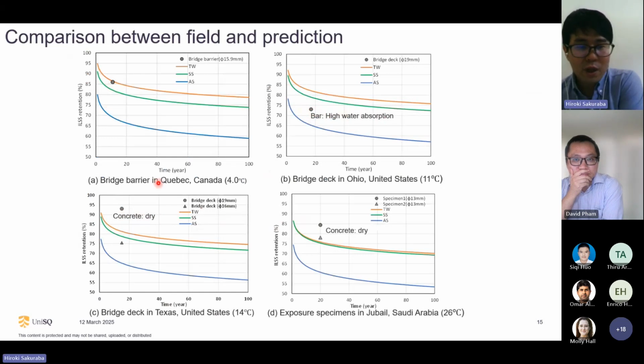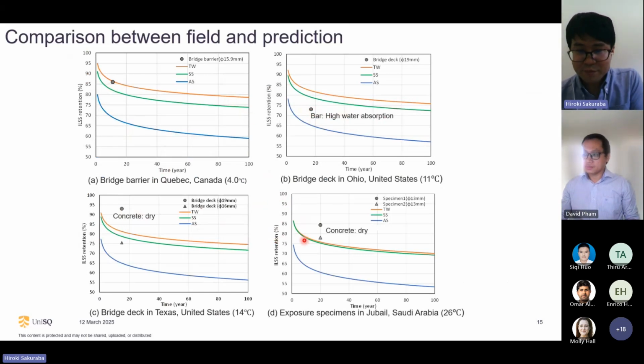But overall, I would like to say the prediction result based on alkaline solution shows a really conservative result. But on the other hand, the prediction result based on tap water or saline solution shows a relatively good agreement.